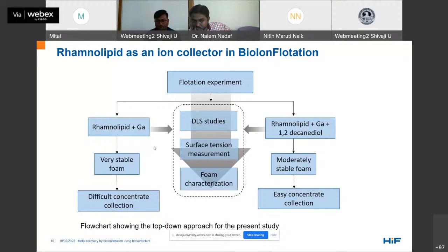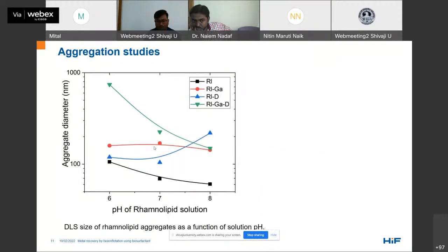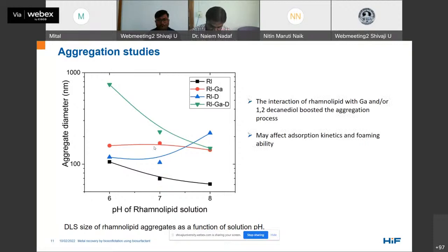So coming towards the aggregation studies, as I said, mixing of rhamnolipid and gallium resulted in the colloidal suspension. So these colloidal interactions were studied using DLS, that is dynamic light scattering. Aggregation behavior of rhamnolipid alone and in presence and absence of gallium and/or 1,2-decanediol was studied as a function of pH. Increase in aggregate size, as can be seen from this figure, indicated that interaction of rhamnolipid with either or both of them boosted the aggregation process, which may affect the adsorption kinetics and foaming ability of rhamnolipid, which we are not sure, and we can see in the later studies what it revealed.